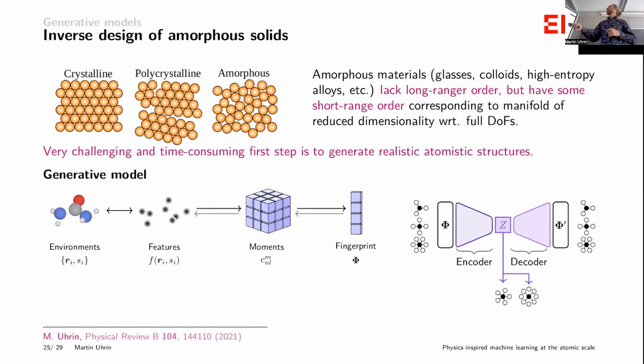So what I tried to do, and in fact, I kind of had this in mind when I did this work, is take this sort of rotationally invariant fingerprint of these local atomic environments, and say, well, can we borrow machine learning models that can help here? This particular model that I've used is called a variational autoencoder. What you can imagine it does is it's a neural network that takes my inputs, which is now going to be this rotationally invariant representation. The number of neurons in each successive layer gets smaller and smaller until a bottleneck, which you of course converge. You find the minimum size bottleneck you can find, and then it opens back out to give exactly the same output as the input that you put in.